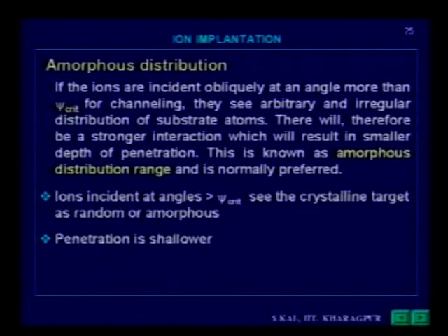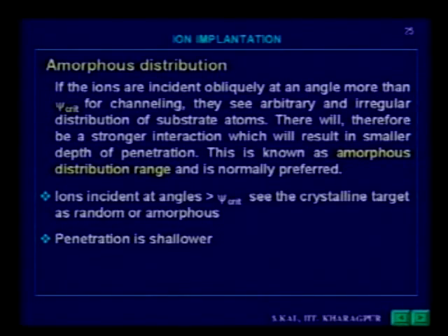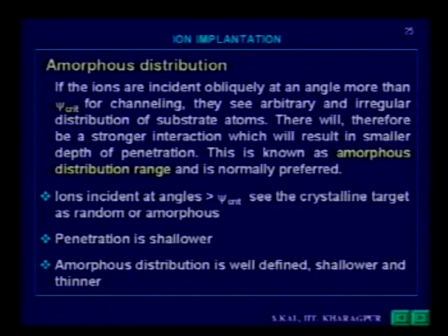Because of the irregularity and the randomness in the position of the atoms, during implantation the channeling will be prevented drastically. Okay, because you are disturbing the regular shape, and then penetration will be shallower. Amorphous distribution is well defined, shallower and thinner. So well defined, shallower and thinner.